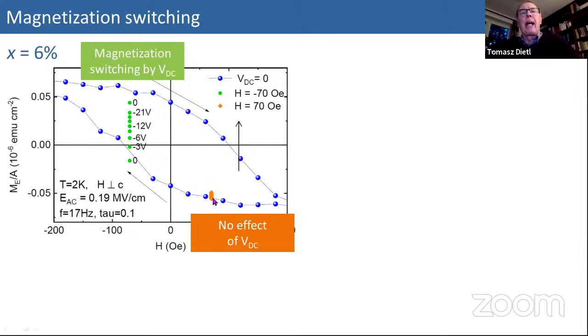And now we switch a large DC field, and nothing happens. This derivative which we measured is shown here by these orange points, and nothing special happens, which confirms what we said before. But the situation differs if we go to negative magnetic field. At this point, we start to switch on an additional DC electric field. We see that this response even changes sign. We switch the sign of magnetization.